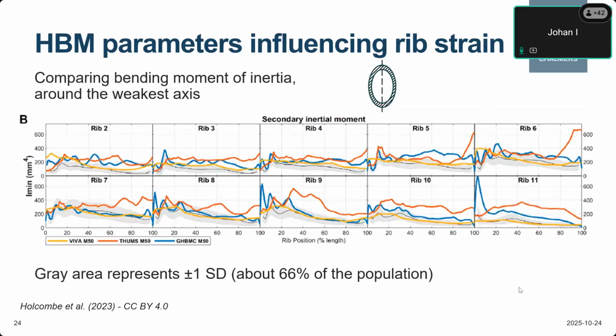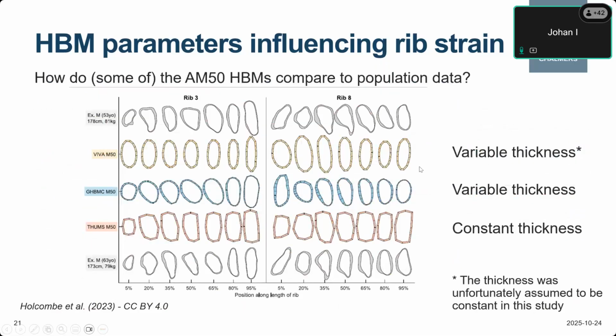And then when you combine this into the bending moment of inertia, and now we look at bending over this axis, the weak axis, then we can see again here that the GHBMC model is maybe a bit on the high side for the upper ones, but quite good for the lower ribs here, while the THUMS model is a bit on the high side for the upper and very high for some of the lower ribs here. So this indicates that I would guess this dimension in the THUMS model, if we go a couple of slides up, so this dimension here, is maybe a bit on the high side for the THUMS model compared to the population that Sven Holcomb looked at. And maybe we can even see that if we compare here the three models, at least for rib 8, one of the lower ribs.